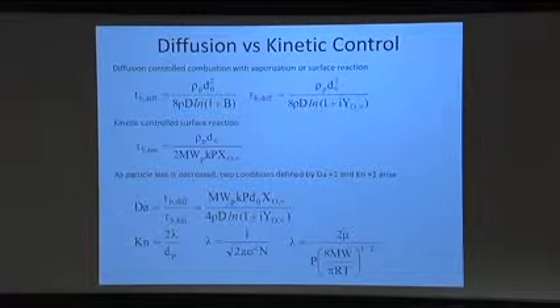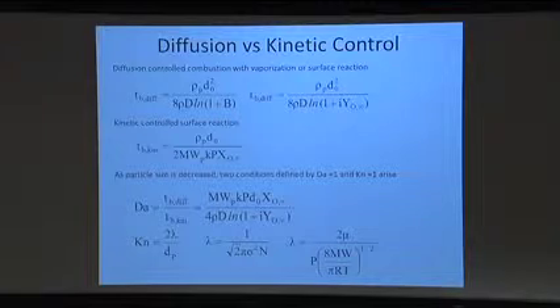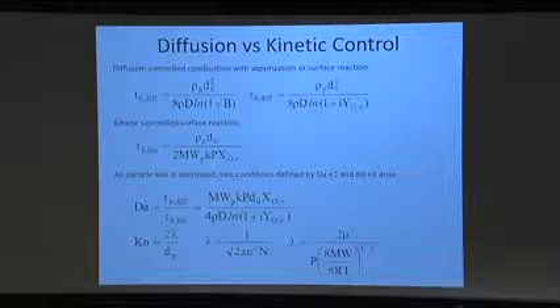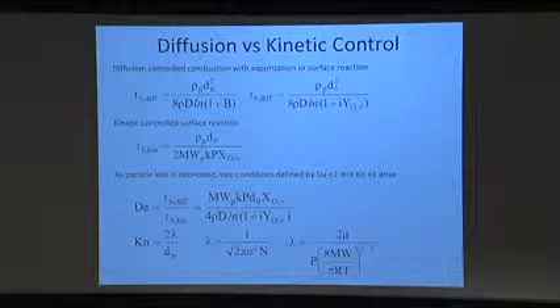If I start looking at the opposite extreme case, I recognize that the rate at which this particle is burning is related to the rate of the surface reaction, and I can go through and derive an equation for, again, the mass consumption rate of the particle, integrate that out, and attain, again, a very simple expression for how long it would take the particle to be consumed under a condition where it's kinetically controlled. And what one typically finds then is now this time is related to the initial diameter to the first power. In addition, you find in the denominator here a pressure term, and this is essentially the rate constant of that chemical reaction. So this is going to be highly temperature dependent here.